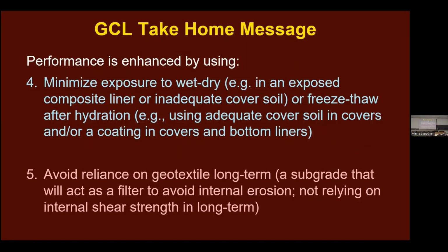Avoid reliance on the geotextile long-term, because it's not going to last forever. The bentonite, if you choose your K value, if it's an appropriate value, will keep it indefinitely. And so, why do I have that till layer below my GCL? Not for its hydraulic conductivity, but because it acts as a filter. If the geotextile goes, I'm not going to get erosion of my bentonite under 40 metres of head, which is what I've got at that dam.